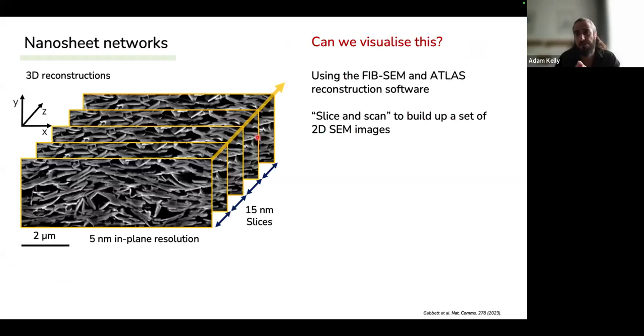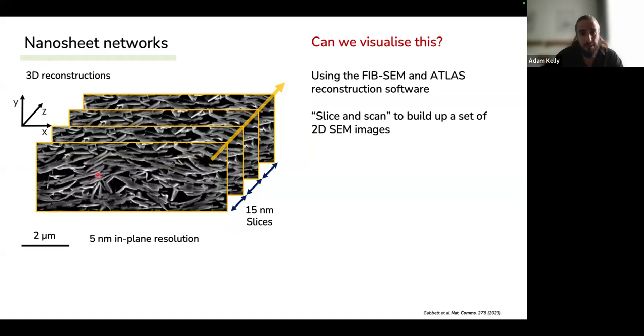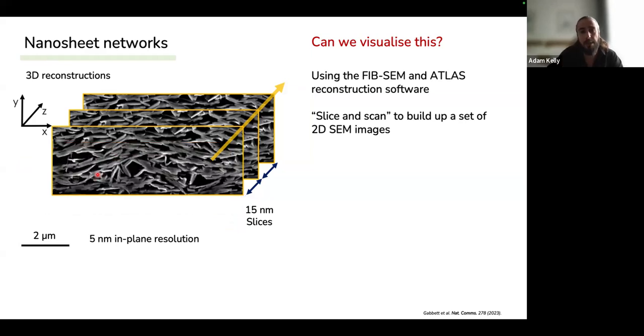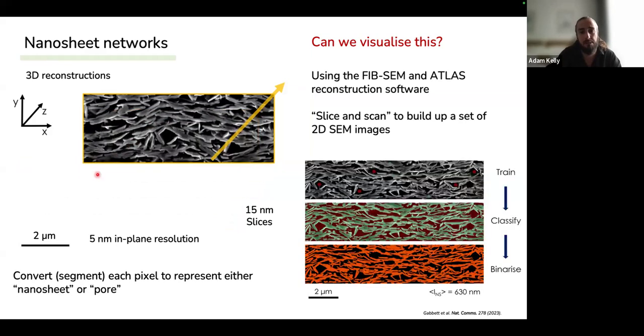One way to do this is using FIB-SEM tomography, and then we can reconstruct these networks using some software. So what you do is you take the FIB technique and you mill a section of your material, of your network, and then you image a cross section using the SEM. Then you increment about 15 nanometers. You do the same again. You mill away your material, you image. You mill, image, mill, image, mill, image. And what this does then is gives you 600 or 700 individual cross sections that have moved their way through the network.